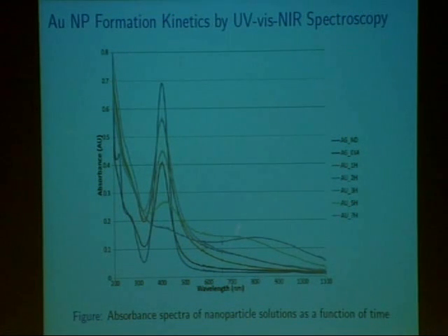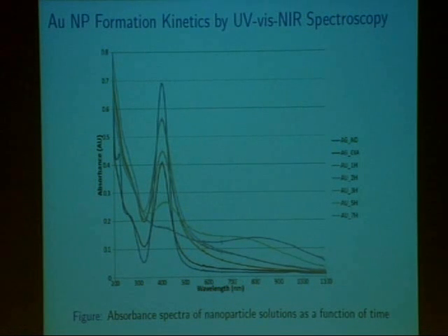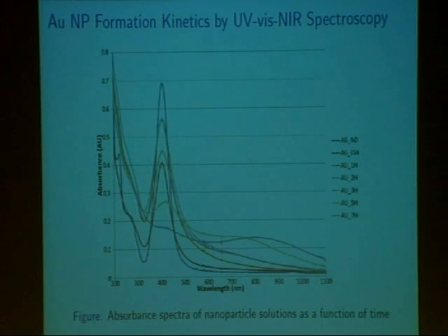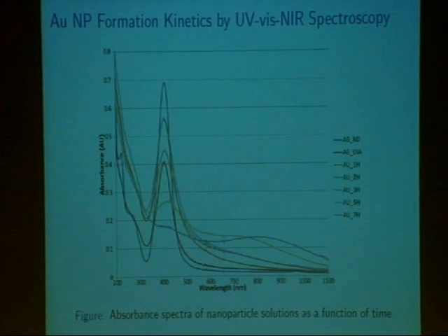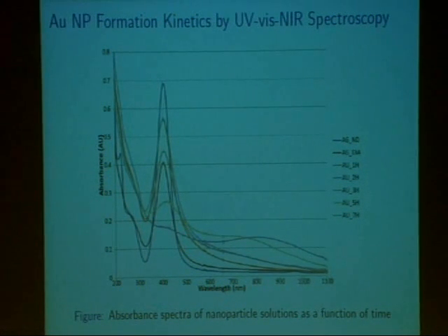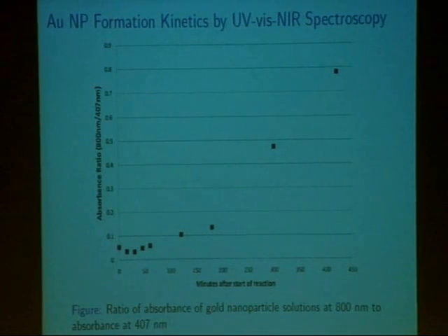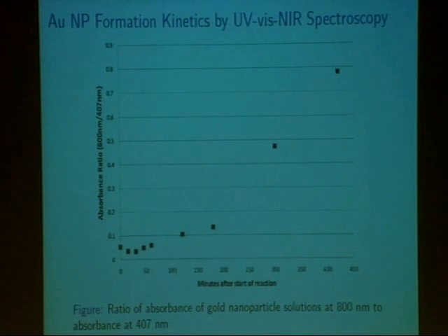At some later time points, you get absorption at 800 to 900 nanometers, which is characteristic of hollow gold nanoparticles. It's difficult to compare between peaks in these spectra because the samples were not diluted consistently. So what we did was take the absorbance at 800 nanometers for each sample and divide it by the absorbance at 407 nanometers — the silver peak — to get a relative gold-to-silver ratio. As the reaction progresses to seven hours when we stop it, the gold-to-silver ratio increases.